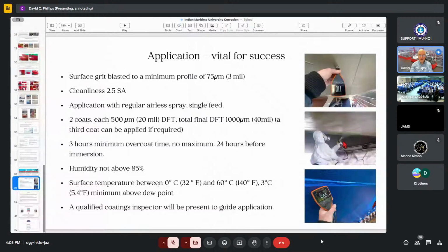With this coating, you can put on the first coat in the block stage. In other words, you can build a block and coat it. And then you can bring all the blocks into the dry dock, put the ship together, weld up your erection joints, which obviously burns the coating at the edges. And then you just have to prepare that little section where the erection joint is, put on a first coat there, and then you can put on the final coat.